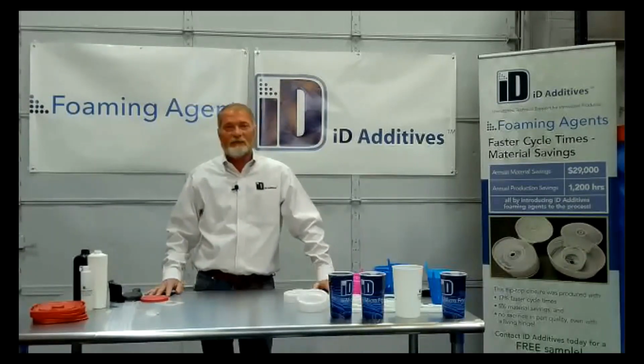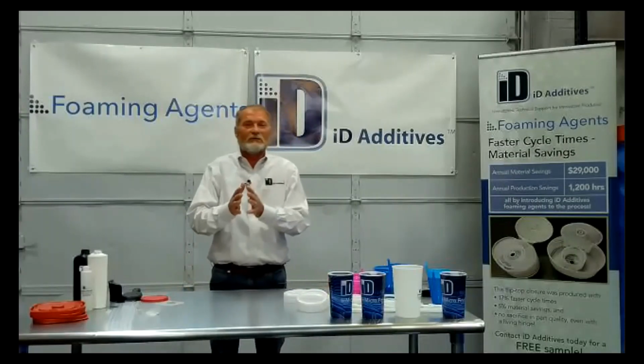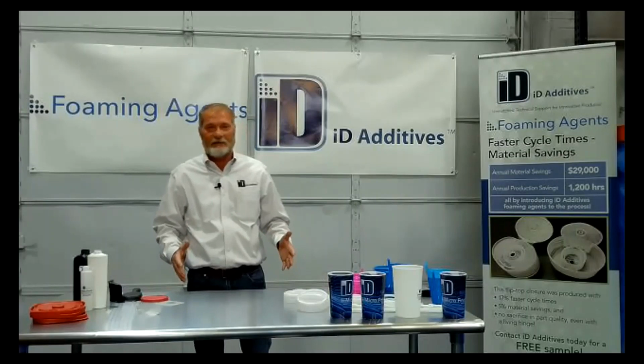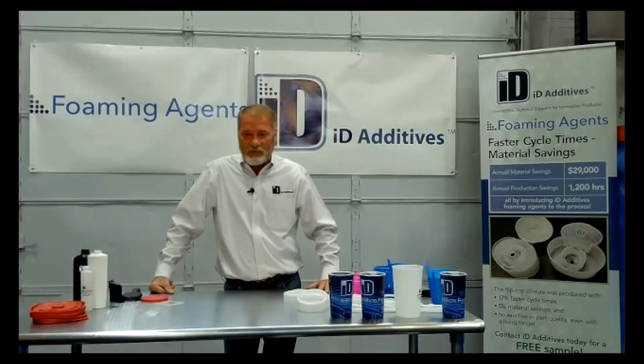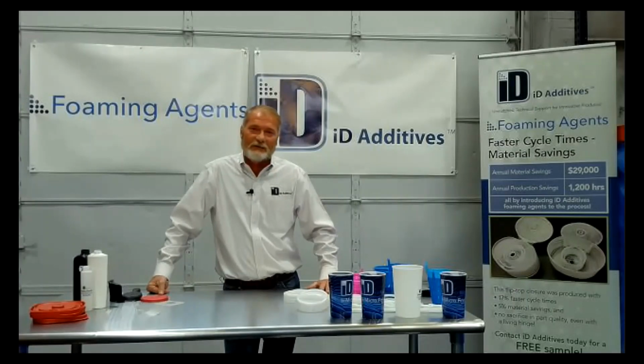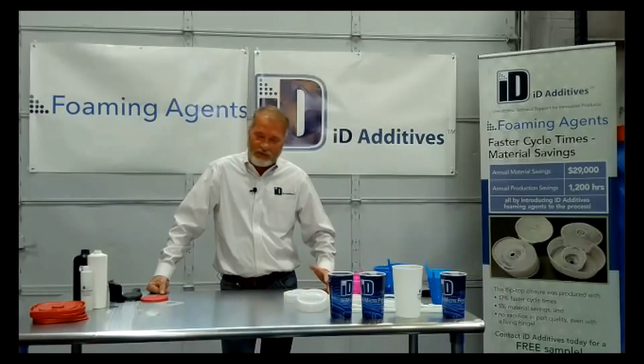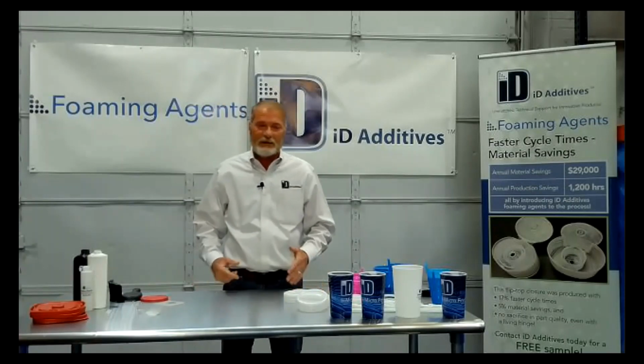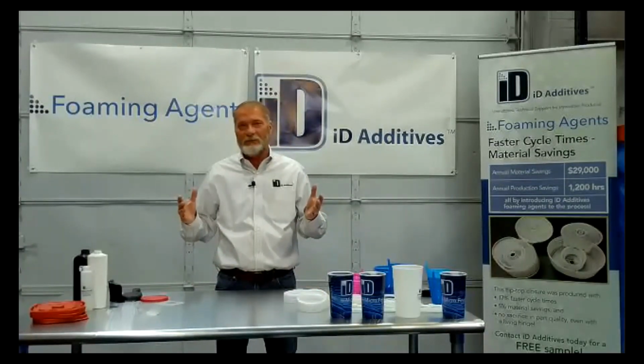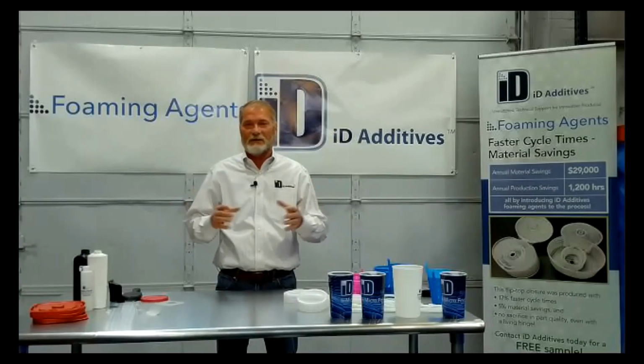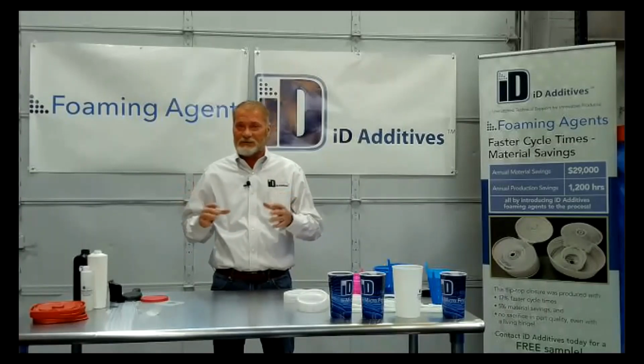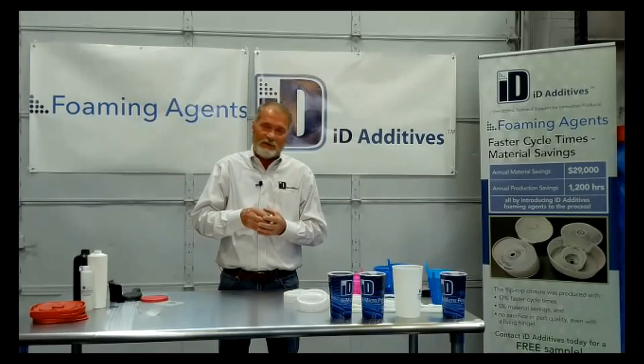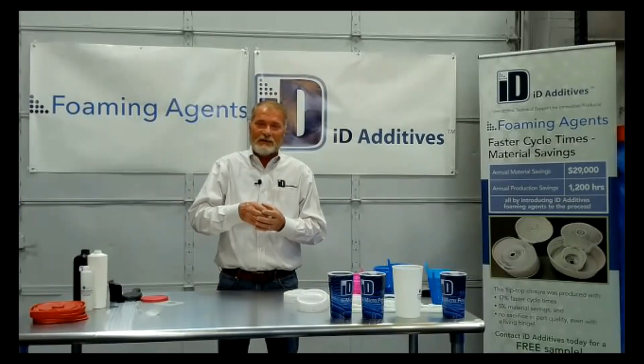So you don't have to have a cavity or a clamp that moves or opens up while you're injecting. You don't have to have that. It'll foam. The thicker the part, actually, the easier it is to foam. And that just depends on how much you want to pull out too. A lot of times with thick, soft materials, you get it in really quick, you run your standard cycle, and you open it up, and they start puffing up on you. Even if you lower the temperatures, it's a soft material. It's got internal pressure from the foam expanding inside, and it's taking up room.